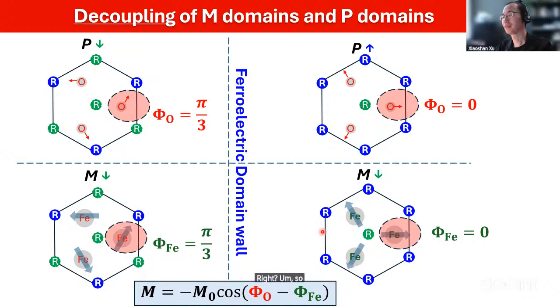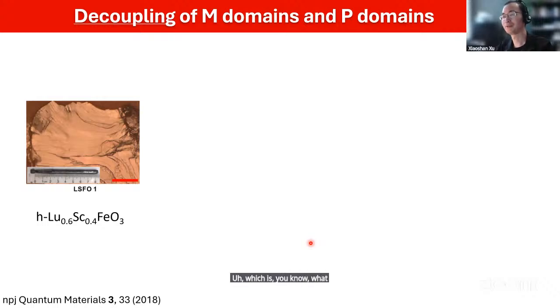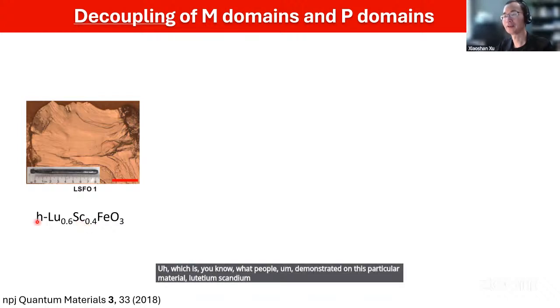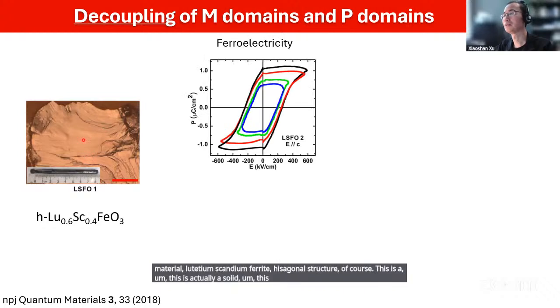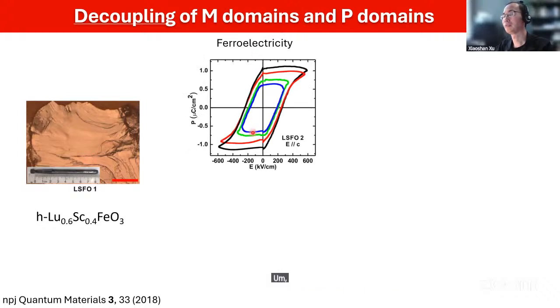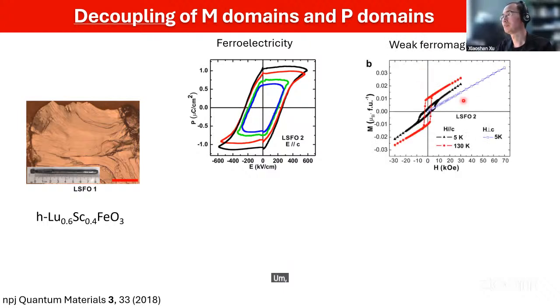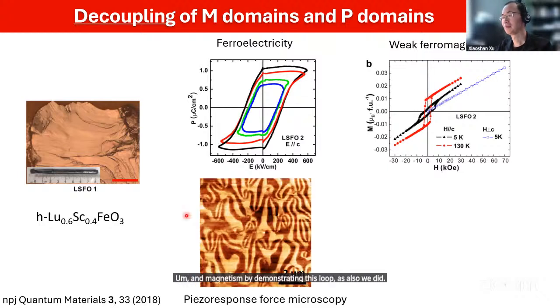So it looks like magnetic property does not care about electric property. If you look at this on this scale, which is what people demonstrated on this particular material, lutetium scandium ferrite, hexagonal structure, of course. This is actually a solid. This is their sample. They demonstrated ferroelectricity by looking at this loop, as we did, and magnetism by demonstrating this loop, as also we did. And then this is the clover-shaped domains as we talk about, right?